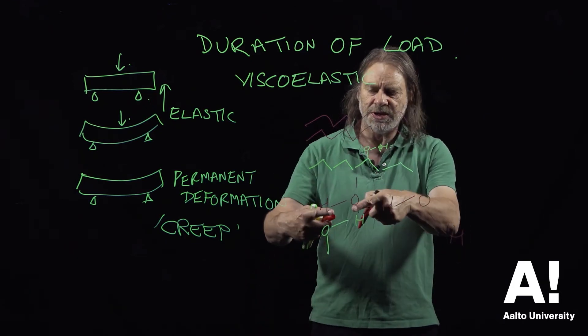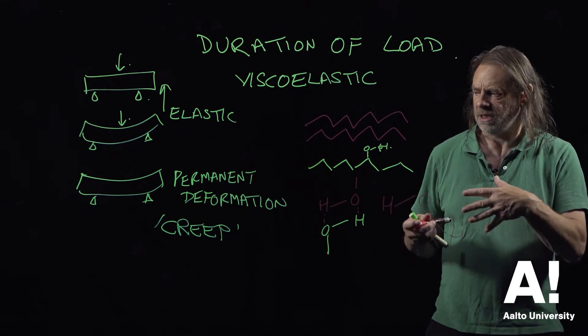It can put itself between these two hydrogen bonding regions. So it acts like a lubricant, or it can act like a lubricant, like ball bearings if you like.